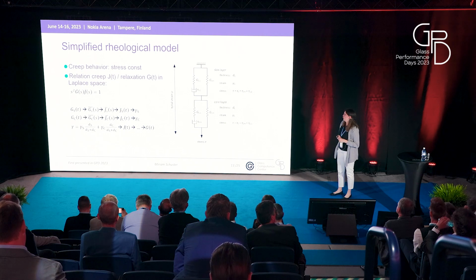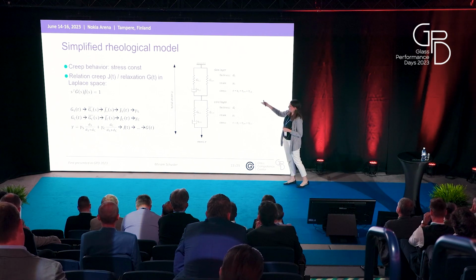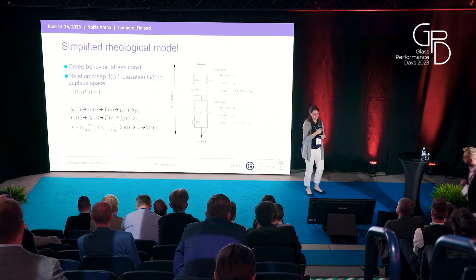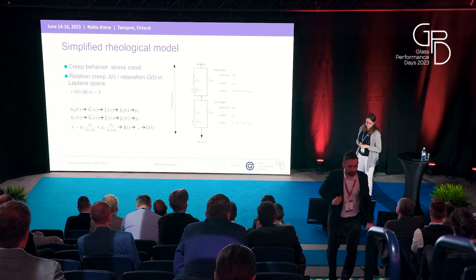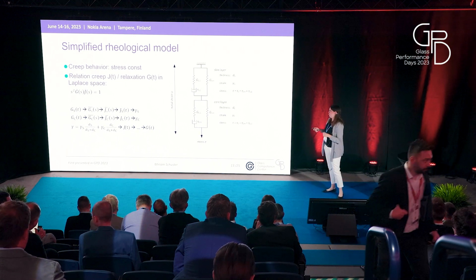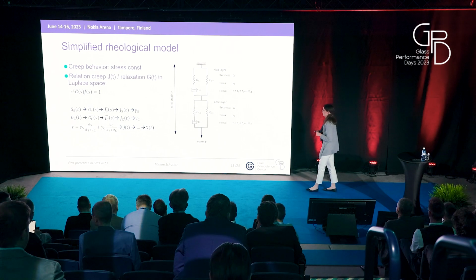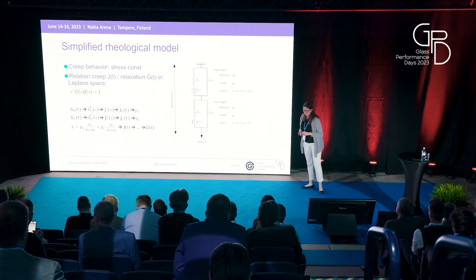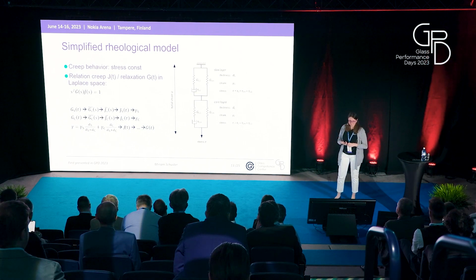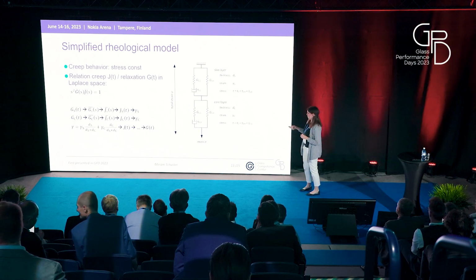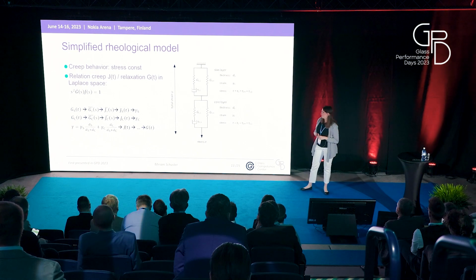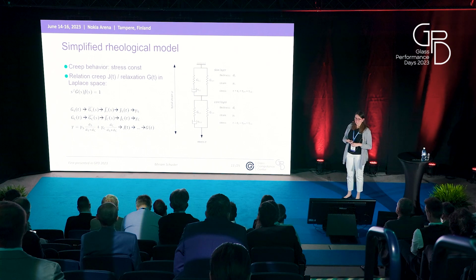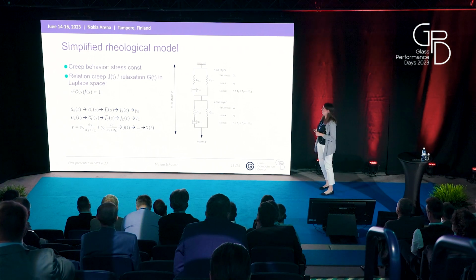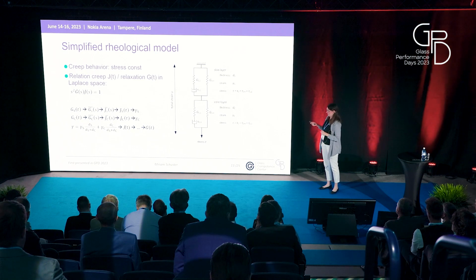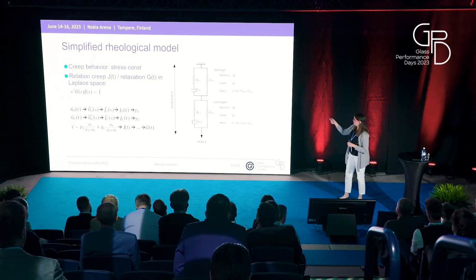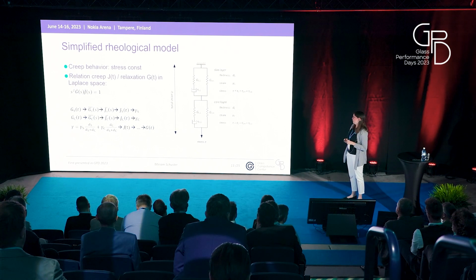So what did we do? We considered our relaxation functions for the individual layers, transferred them into the Laplace space, then used the relation between creep and relaxation, used the inverse Laplace transformation to get the creep function, and then were able to determine the creep strain for each of these layers. And then we could calculate the total creep strain. With the total creep strain and the applied stress, we can calculate the creep function, and again, using Laplace space, we can transfer this back to the relaxation function. So this seems also very complicated at first sight, but in fact, this is a really short code in MATLAB, and it is also really fast to calculate, even if we are considering more material parameters for the individual layers.